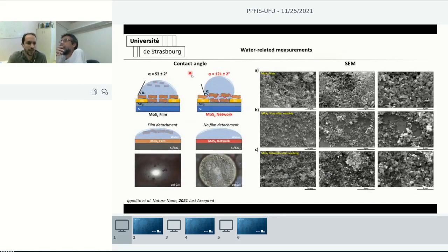It happens as well. So here we have the surface contact angle of films and networks. For films, the surface is quite hydrophilic, presenting contact angles around 53 degrees. What we also observe for films, so no molecules involved, is that some flakes float in the water drop, meaning that there is some detachment of flakes when you expose this film to water. For networks, so flakes bridged together with the BDT molecules, the contact angle is higher, around 121 degrees. This is because the BDT molecule, the benzene core, is quite hydrophobic, and there is no detachment. So this is evidence that the molecules are doing their role, that they are bridging flakes together.